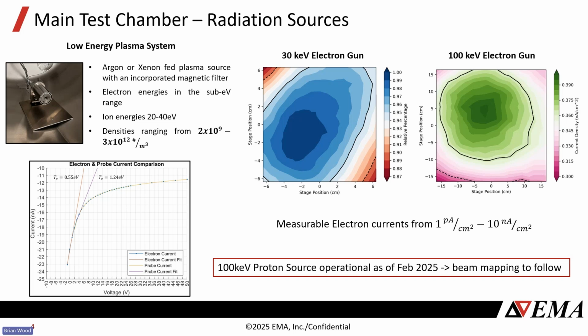We usually use argon. We've used xenon before. But we choose these densities to, again, try to represent whichever environment the customer is looking for. So there's typical LEO densities. If you're trying to go really low to represent more interstellar densities, we can do that. If you want even higher densities, that is a concern sometimes if you're in LEO and you're operating a plasma thruster, where that plasma thruster is actually contributing to the ambient plasma around the spacecraft, then you would use this device to simulate that.